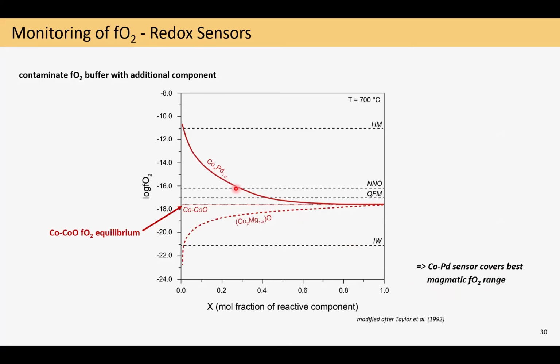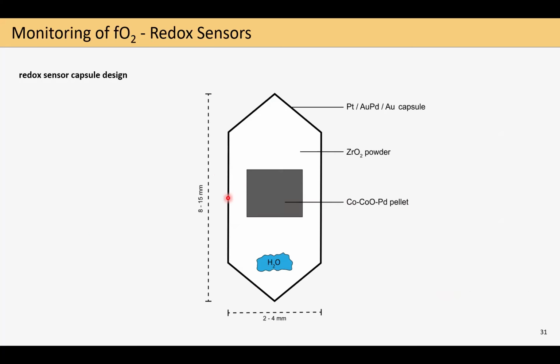And this is what we just did in a recent study. But wait, before I go to that, first I want to show you what these sensors look like. We normally have just a noble metal capsule with a cobalt oxide, palladium pellet made of powder, enclosed in zirconia powder, and some added water, which we need to allow the sensor to adapt to changing fO2 conditions. The zirconia powder is there to protect the sensor from any alloying with the noble metal from the outside.